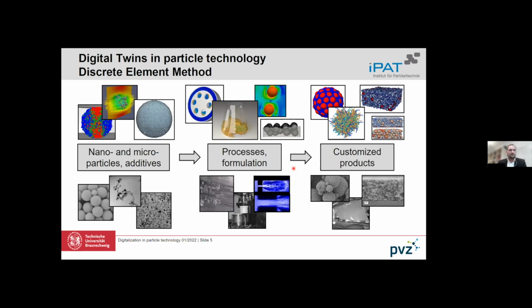And if we now start with the discrete element method or the classical numerical modeling, state of the art is that we are able to simulate nearly all particulate processes along the whole process chain, starting from the particle synthesis and surface modification, the formulation of particles and the further processing, as well as the resulting particulate structures and their properties. That could be, for example, a spray drying process or a dispersion process in a dissolver. That could be like this. This is a CFD-DEM simulation of a stirred media mill.